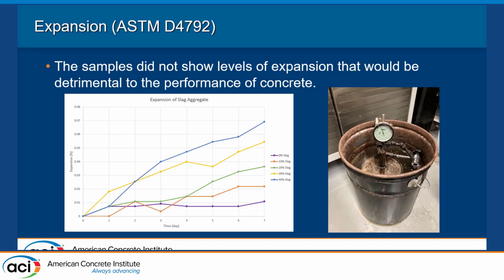So the main tests that were completed during this research were ASTM D4792, which is the standard test method for the potential expansion of aggregates from hydration reactions. And this test measures the volume expansion of dense graded compacted aggregates. Samples for this test were prepared using a modified California bearing ratio test, which had to be modified for use with coarse aggregate as opposed to the traditional finer soils. This test was performed on samples of 100% traditional limestone coarse aggregate, as well as samples of limestone aggregate supplemented with 10, 20, 30, and 40% electric arc furnace slag by volume.